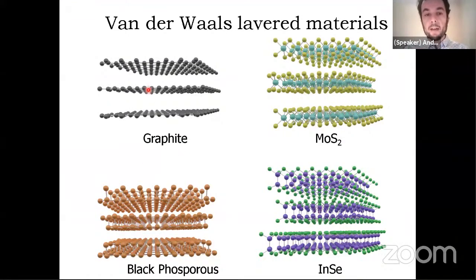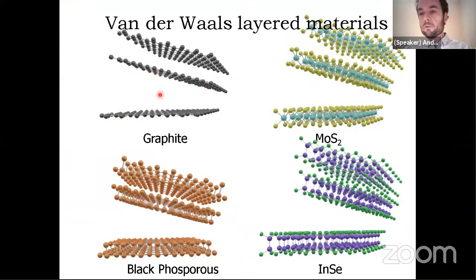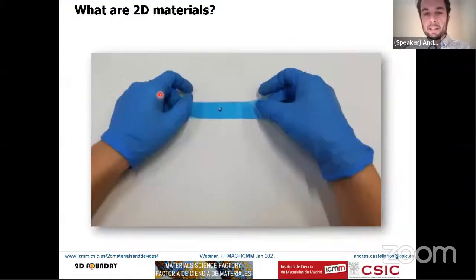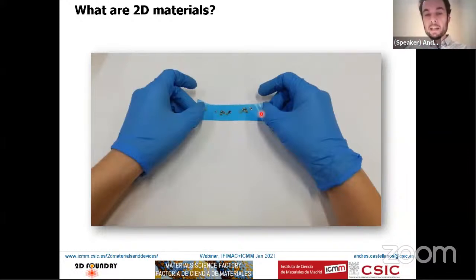Okay, so in the case of graphite, for instance, we have these strong carbon-carbon covalent bonds in plane that form these layers. And between the layers, we have just weak van der Waals forces. So we have a huge anisotropy in the strength of the bonds between the in-plane direction and the out-of-plane direction. And that makes our life easier if we want to isolate thin layers, because then we can easily cleave these crystals, just using, for instance, a Scotch tape. Basically, the process that we use to isolate two-dimensional materials, the so-called Scotch tape exfoliation method, is placing a single crystal on a piece of tape. This blue tape is a specialized tape, but you can also use normal Scotch tape. And then by folding and peeling, we can cleave the crystal.